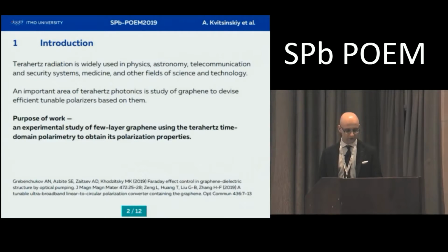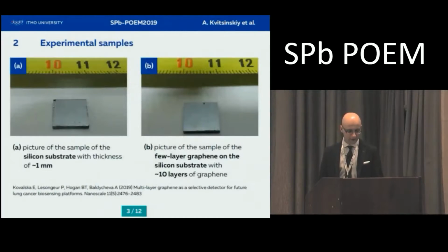And so our purpose of this work was an experimental study of few-layer graphene using the terahertz time domain polarimetry to obtain its polarization properties. So, a few-layer graphene on a silicon substrate and a silicon wafer as a sample of this substrate were chosen as experimental samples. This 10 layers graphene sample was synthesized at University of Exeter, UK on a nickel substrate by the chemical vapor deposition in quartz furnace and then transferred to a silicon substrate with thickness of 1 millimeter.